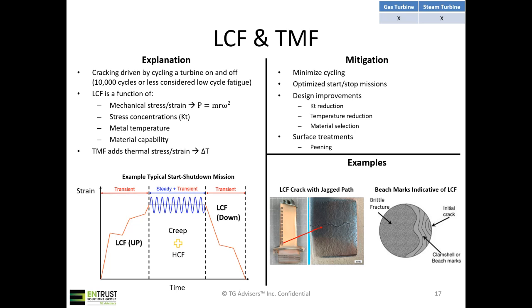The other thing that you'll really see when you start looking under the microscope is that the fracture surface will have what we call beach marks. Each of those individual beach marks represents one cycle, or one on and off. So that's one thing to look for as well.